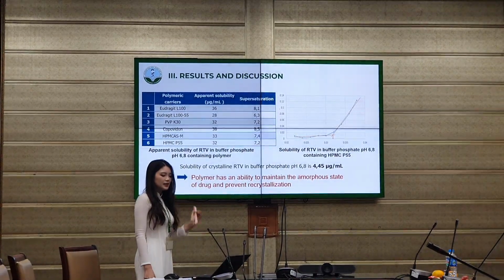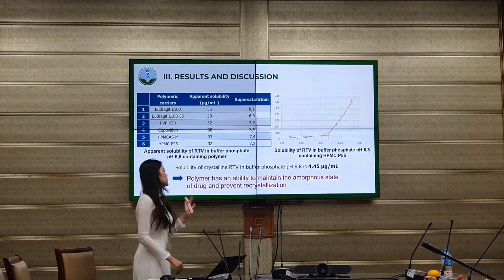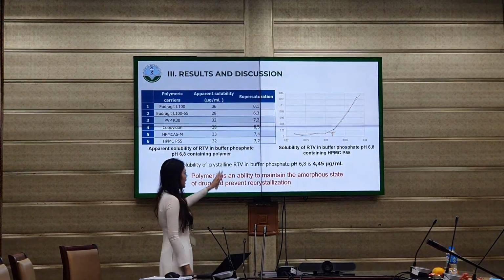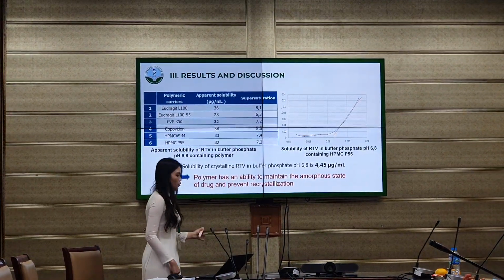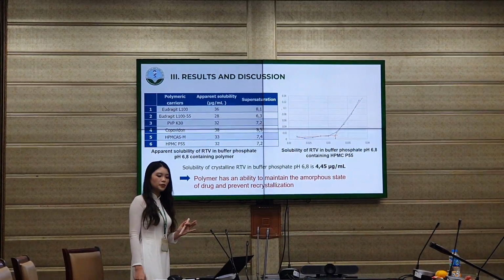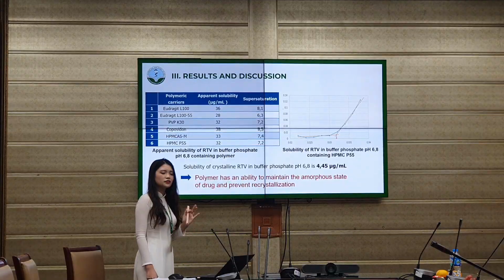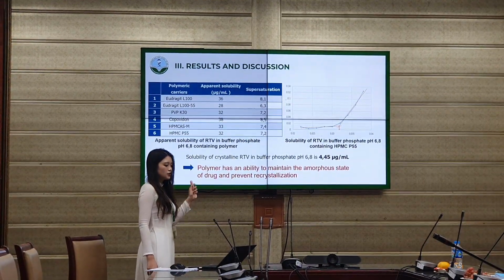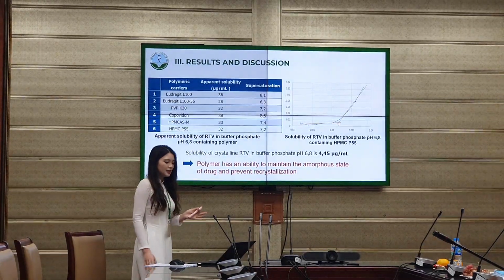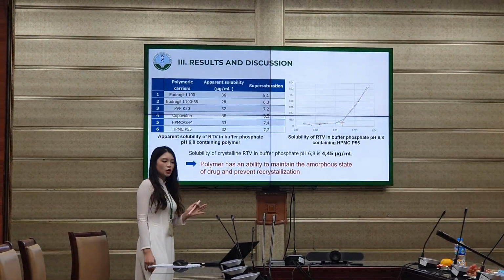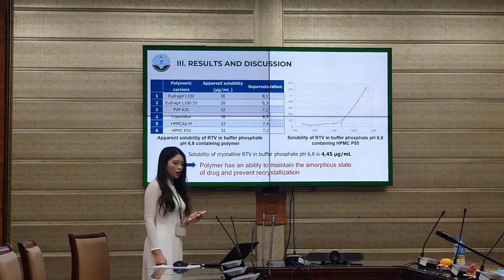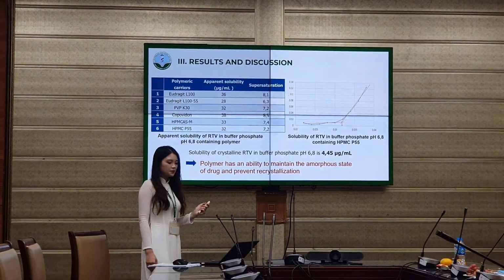Apparent solubility determination of the drug was carried out using light extinction, and the measurement results were presented as a line graph to determine the cloud point of the solution. The assay was conducted at 350 nanometers, a wavelength that the drug itself does not absorb. As the solution begins to precipitate, light scattering increases, leading to a sharp rise in the absorbance. This inflection point is referred to as the cloud point, marking the onset of visible turbidity.